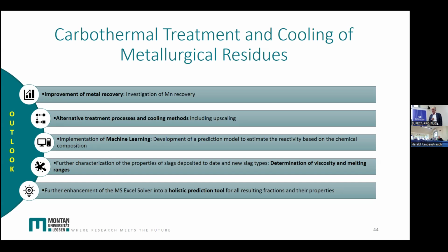And what is really crucial is to determine the viscosity and the melting range of the slag. It would be nice to measure the viscosity in situ. Now we have to measure somehow the temperature, and even that is not too easy, to measure the temperature of a slag, as you know. And then calculate the viscosity. So it would be nice. That's a problem for the glass industry as well. If you could measure the viscosity of the glass phase when it fills the forms for forming the bottles, and if you could measure the viscosity inline, it would be a big advantage.